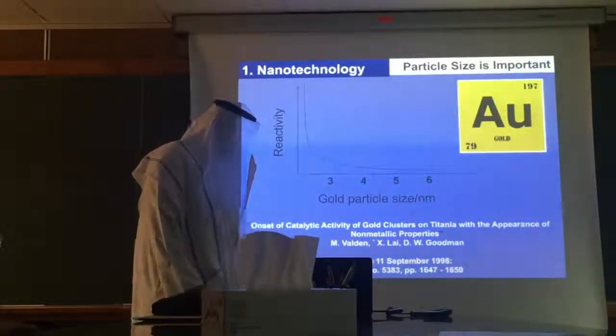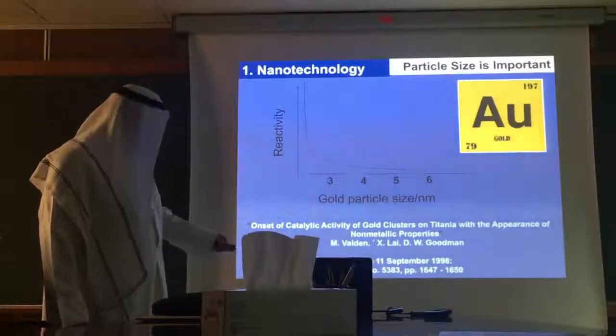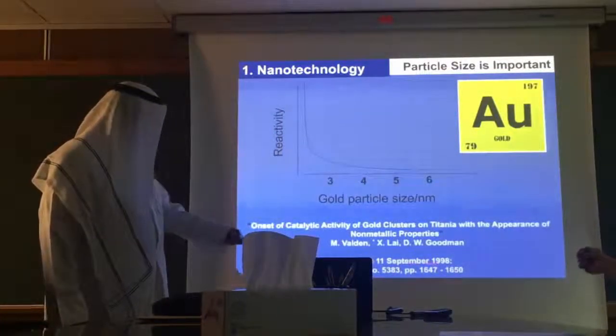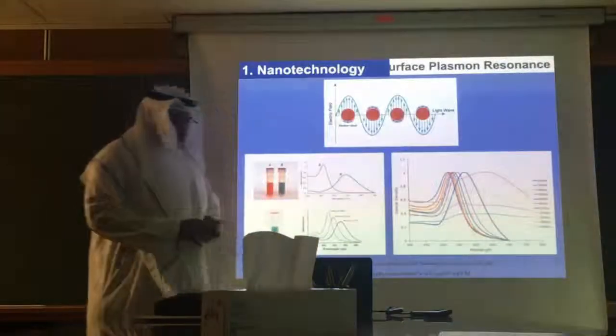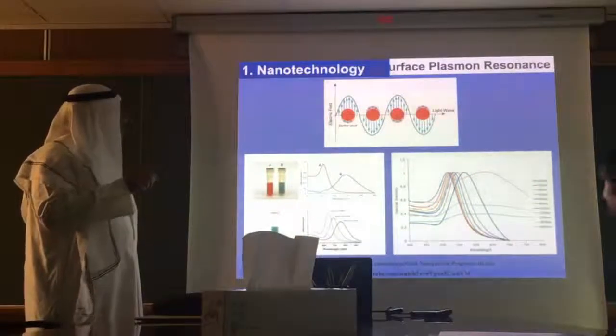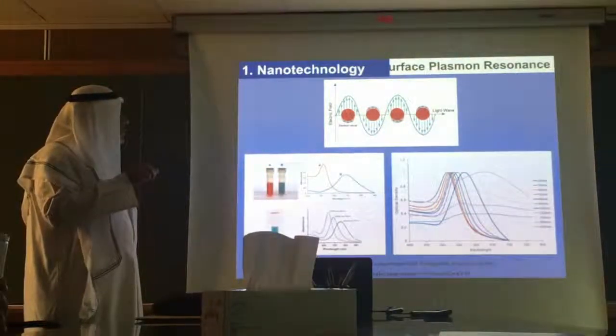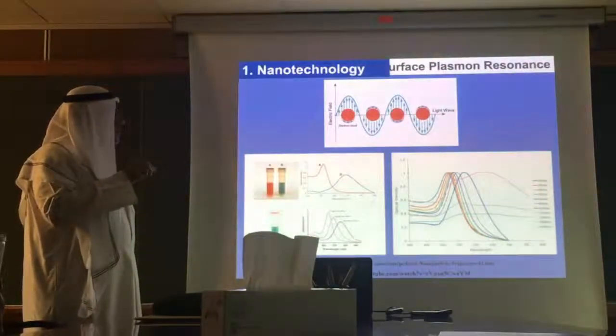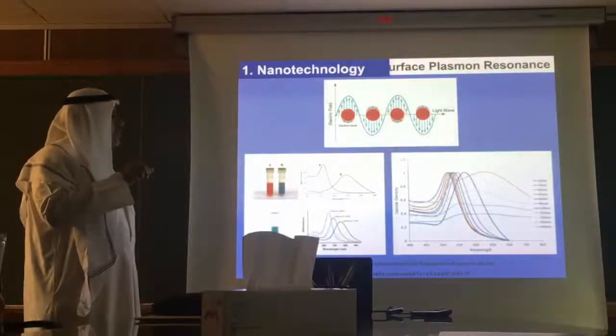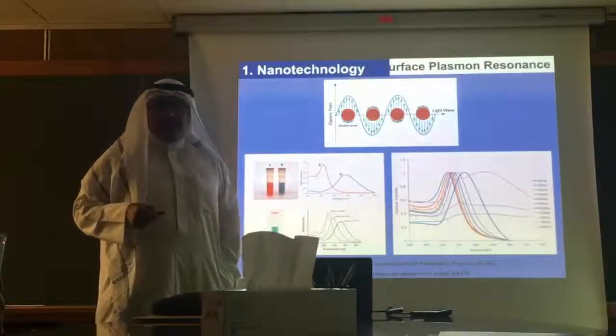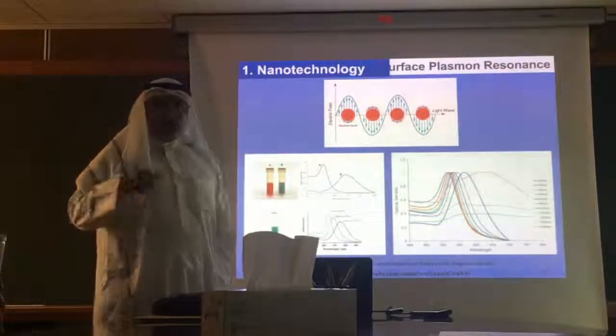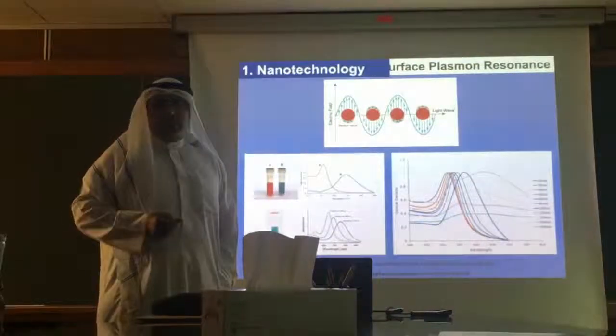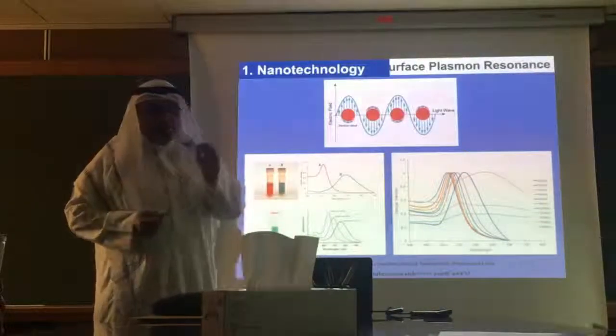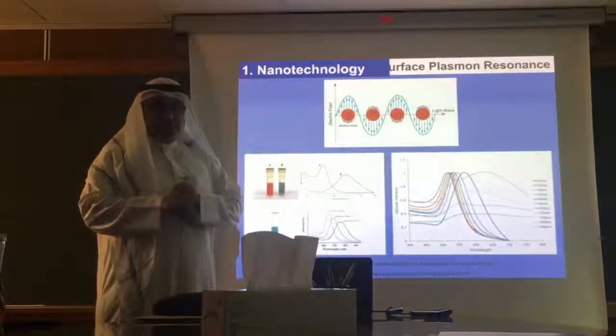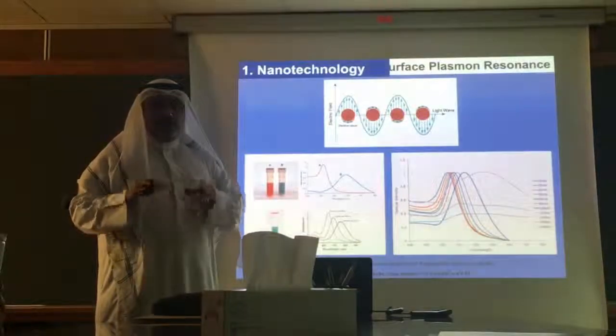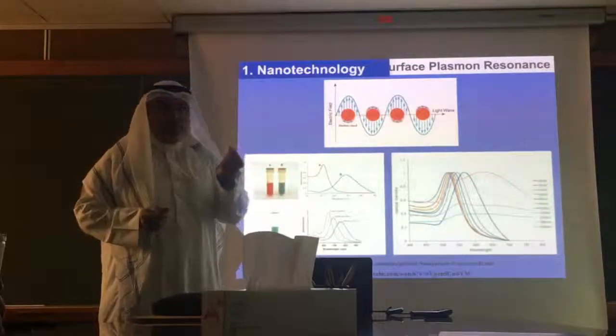And because this was very important work, it was published in Science. I don't know which year, maybe 20 years ago. When you expose gold nanoparticles to visible light, the electron clouds start to oscillate, so there will be partial negative here and partial positive there, and then the opposite. Because of this oscillation, heat develops, and the temperature of the nanoparticles increases suddenly; it can reach up to 1,000 degrees. If you make it very small and make it stick to a cancer cell, for example, it will only destroy the cancer cell. It will not destroy the neighboring cells because it is very small, nano size.